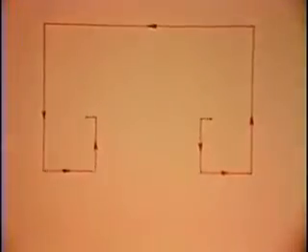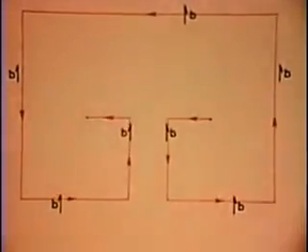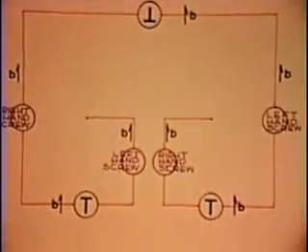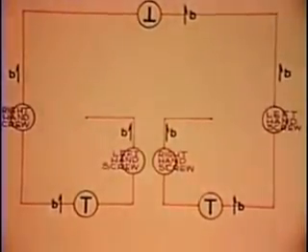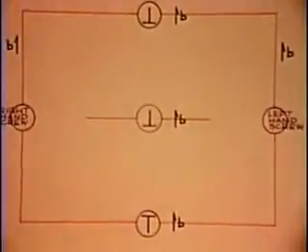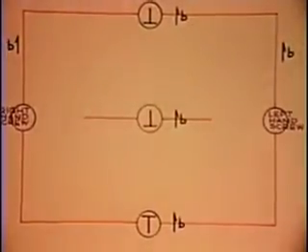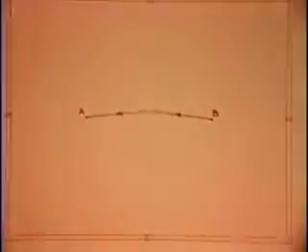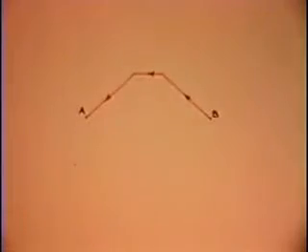Thus, the top edge segment has its extra half plane above the slip plane, and the bottom ones have their extra half planes below. The screw segments, moving towards each other, have opposite twists. Once they annihilate, the loop is free to expand, and the recreated initial segment bulges out to produce a second unit of slip.